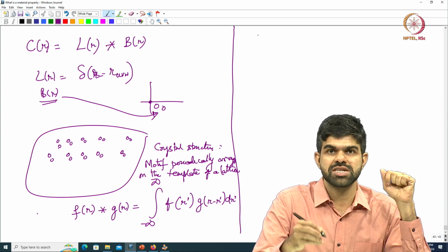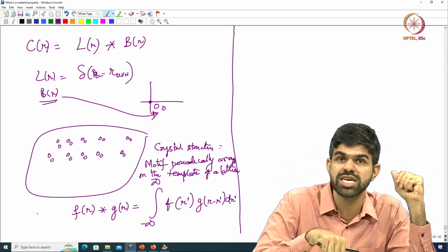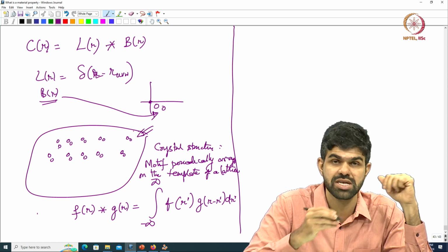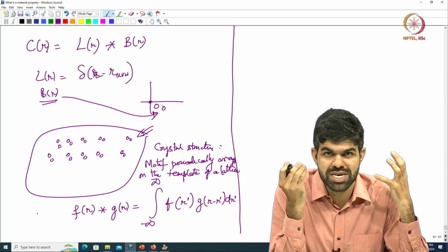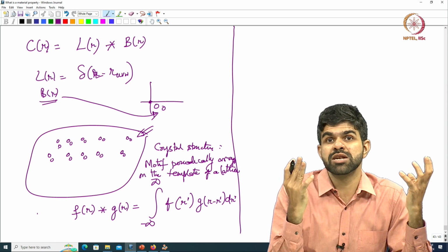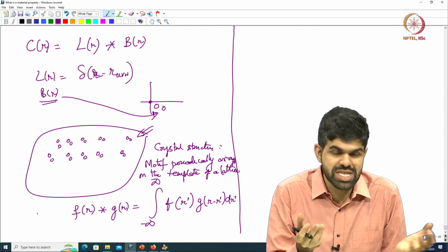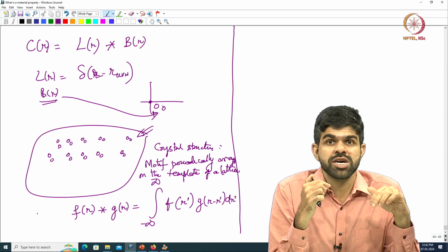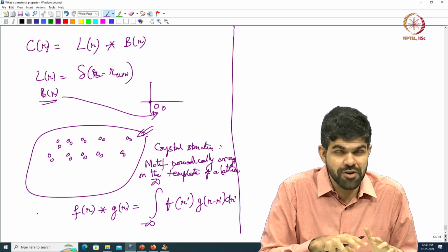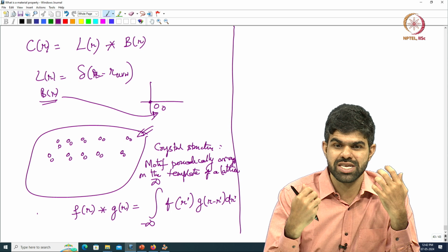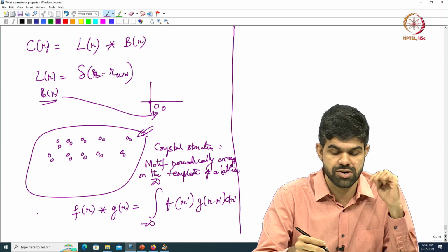Okay, so with that definition of crystal structure, when I do a microscopy or X-ray diffraction experiment, all I am trying to get to is this crystal structure. So, I see the arrangement of atoms as given here, and from this I have to extract the underlying lattice, the underlying unit cells and the underlying symmetries. That is how experimental problems typically are. Seeing the periodic arrangement of atoms is easy nowadays; you can see it using high end electron microscopes, which are there in a lot of places. However, extracting the structure and symmetry of the periodic arrangement that you are seeing, that is the challenge. So, we will formulate it a bit, and then we will be able to identify these things later on.